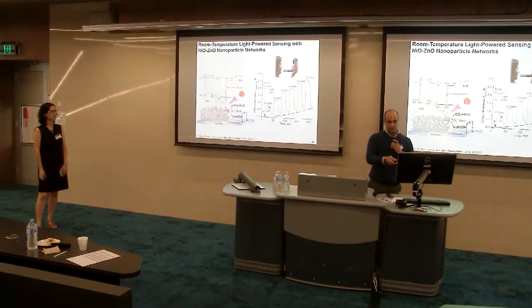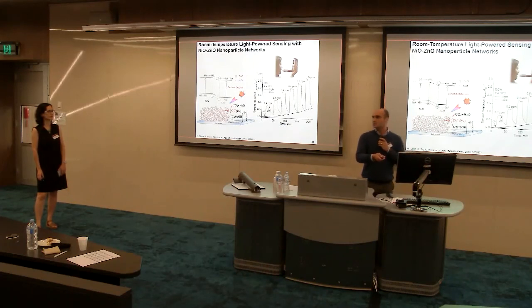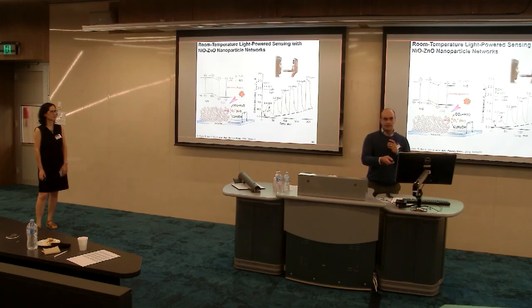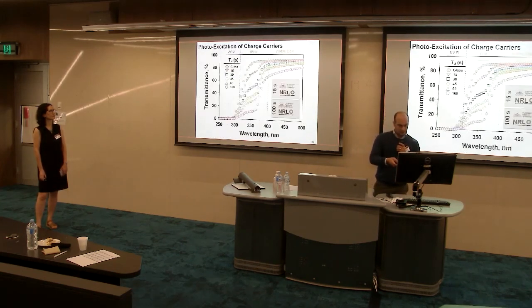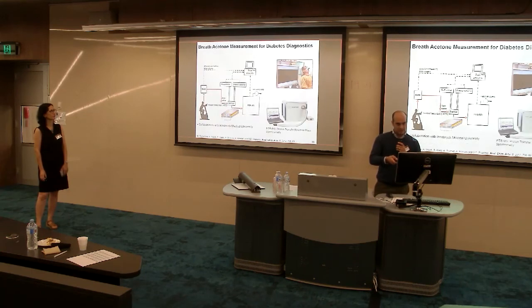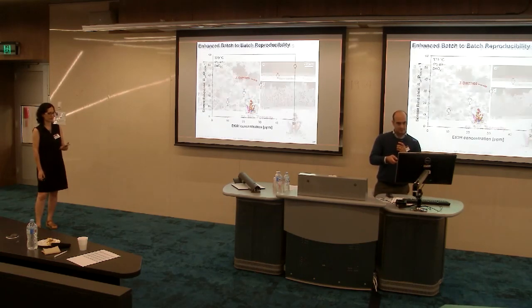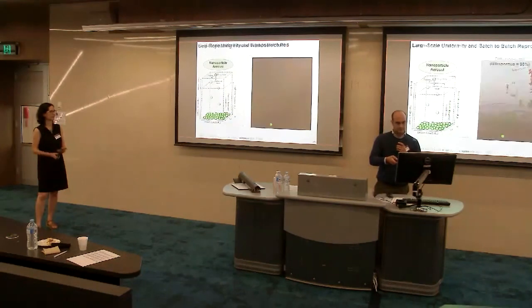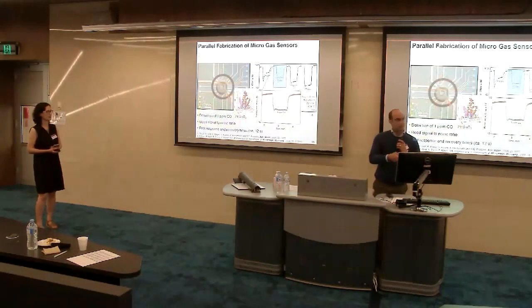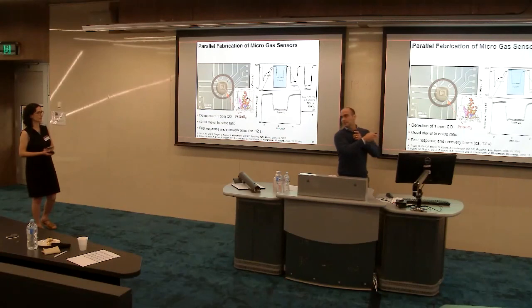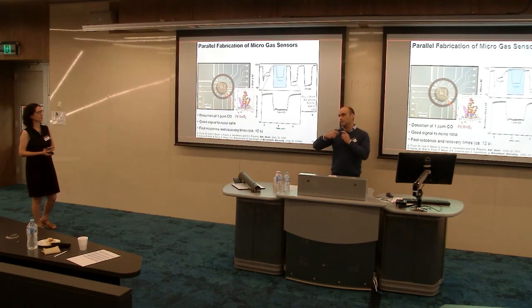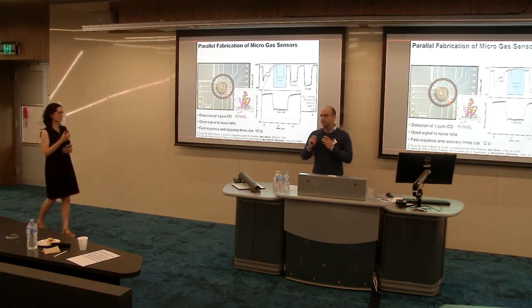So that one, sorry, just a second. This one shows, for example, room temperature, 30 degrees response, you see, with light. And without light, the black line, doesn't work. The other one is the thing I showed you at the start. So sorry, just a second, here we go. So these things - here is a micro plate, relatively standard and simple. You have a silicon substrate, you etch it from the back to make a membrane. On the top, you have two platinum heaters, a temperature sensor, and a set of interdigital electrodes. But yeah, sometimes those things have some issues too.